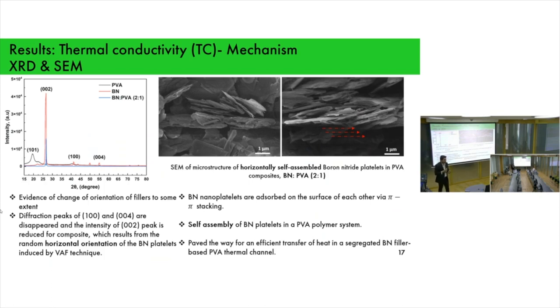Similarly, if you see the XRD analysis, you see a slight change of orientation of fillers, which can be seen by the disappearance of the diffraction patterns of the 100 and 004 peaks, which are reduced for the composite. This results from the random horizontal orientation of BN platelets in the PVA.